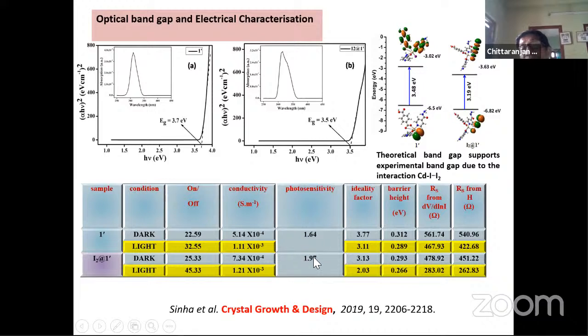And this photosensitivity leads to, you see, the iodine absorption leads to decrease in the barrier height. Barrier height in the dark phase is around 0.312 electron volt, while in the light phase it is decreased to 0.289. While the iodinated system, its dark phase barrier height is 0.293, while the light phase is 0.266. That means both iodinated phase and non-iodinated phase solvent-free system, both are active towards the light radiation to show its conductivity as well as the resistance.